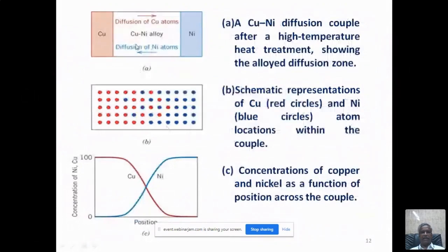You can see here in this diagram, you can understand clearly. Copper atoms move towards this direction, and nickel atoms move towards this direction from nickel. From copper, it is moving here. In this case, copper and nickel, the atom size is almost similar, so they are replacing. If a nickel atom moves towards this side, a vacancy is produced here. That vacancy is filled by the copper atom, which is moving in the opposite direction. Like that, the vacancies created by the movement of atoms will be filled by the movement of atoms from the other side. After diffusion bonding, if you measure from the center to the top surface, the copper concentration will vary, and the nickel concentration also will vary, as shown in this graph.